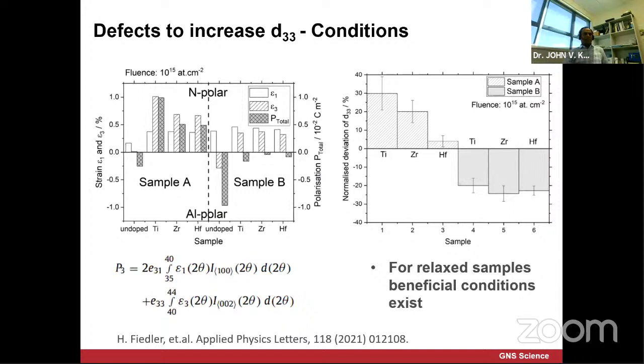So even if you take relaxed samples, with even a tiny amount of doping we can strain engineer them, which will increase the D33 by an order of magnitude. So we have been looking closely at each element, like hafnium and titanium, and looking at the distribution, how this corresponds to the fluences and also to the D33. So this gives you a rough idea of the overall information.